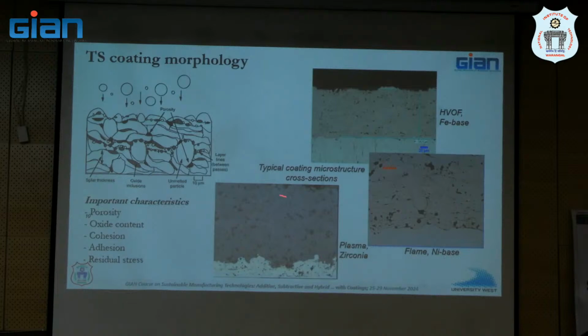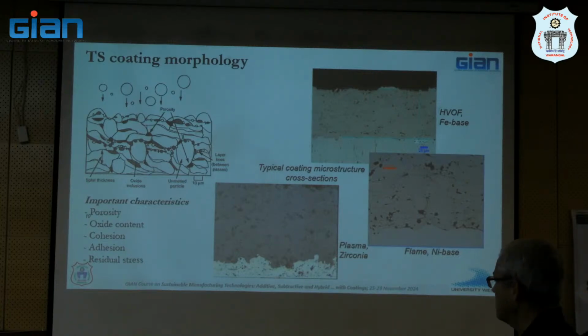These are plasma sprayed zirconia thermal barrier coating. Fair bit of porosity, but porosity is good in a thermal barrier coating. Why is it good? There are a couple of reasons why it is good. I would like to hear at least one. Why is porosity good or okay in a thermal barrier coating? Reduce the heat? Yeah, it kind of reduces the thermal conductivity of the coating, which is what you want if you are putting on an insulating coating. What's the other reason?